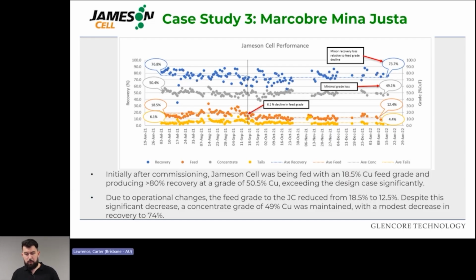Now, because of some operational changes and optimizations, the feed grade to the Jameson cell reduced from 18.5% to 12.5% copper. Now, despite this quite significant decrease, the concentrate grade of 49% was maintained, and recovery did drop a little bit, but only to about 74%, despite that huge decrease in feed grade.